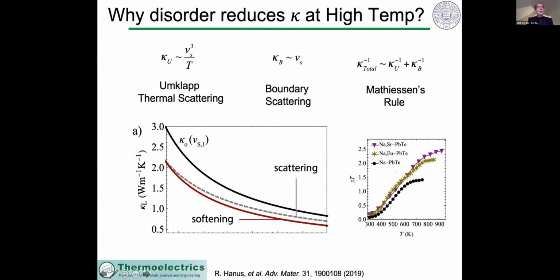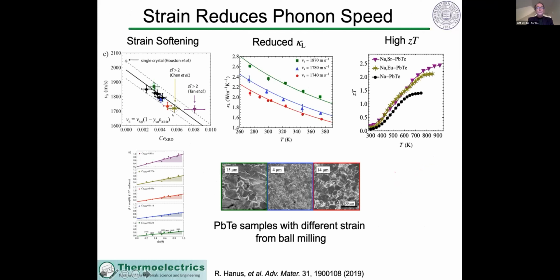So a reduction of the speed of sound that we see experimentally, we'll see in a minute, or basically the speed of the transport as opposed to a scattering. A scattering should have very little effect at the high temperature. So we've seen a softening effect due to a strain in a material.